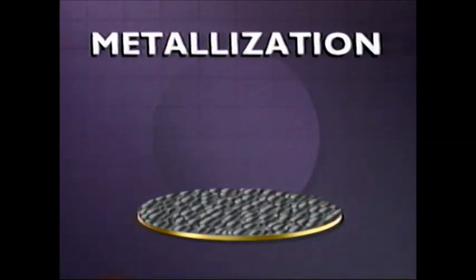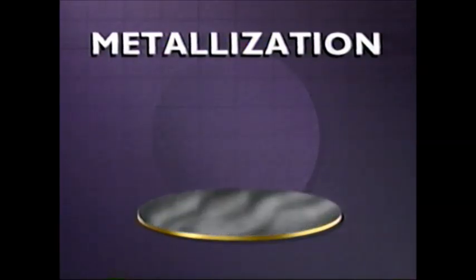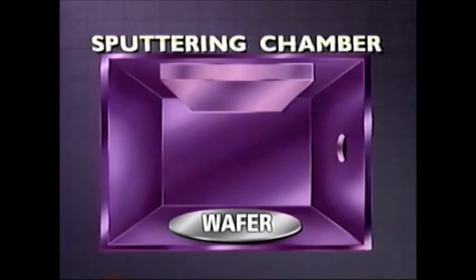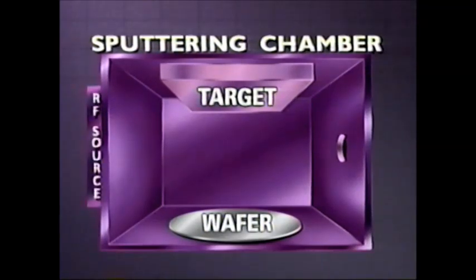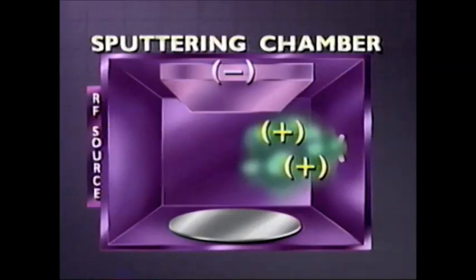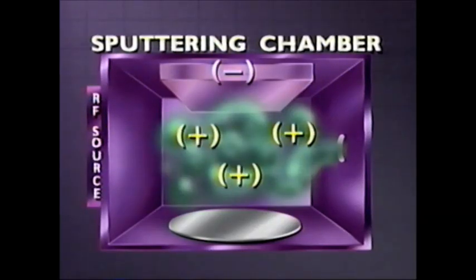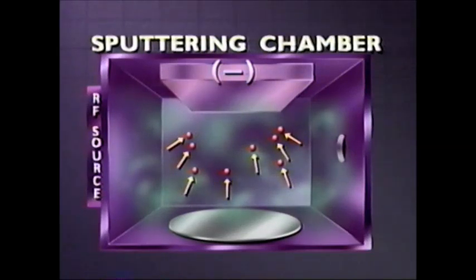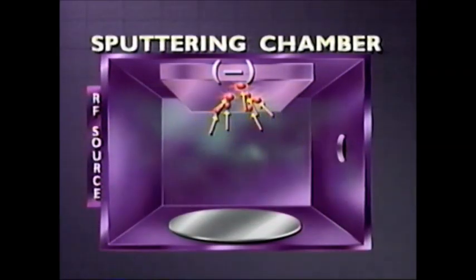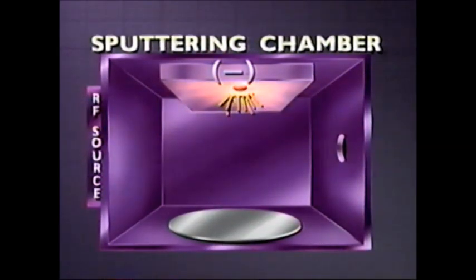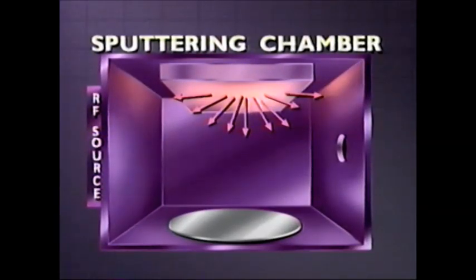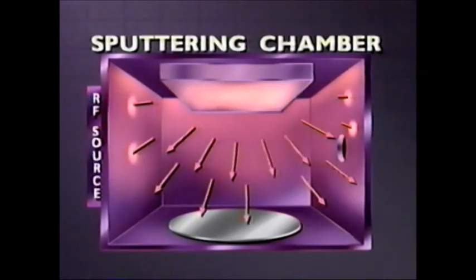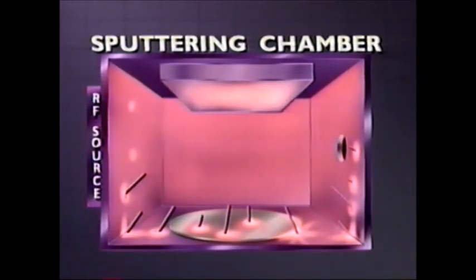During sputtering, the method commonly used to deposit metal on a wafer, the wafers are mounted in a chamber which includes a target, a plasma source, and an argon gas source. The target is held at a negative potential, while the argon ions are positively charged. The positive ions are accelerated toward the negative target. The argon atoms hit the target at a high rate of speed, breaking off some of the target. The minute, broken-off pieces land on everything in the chamber, including the wafer.